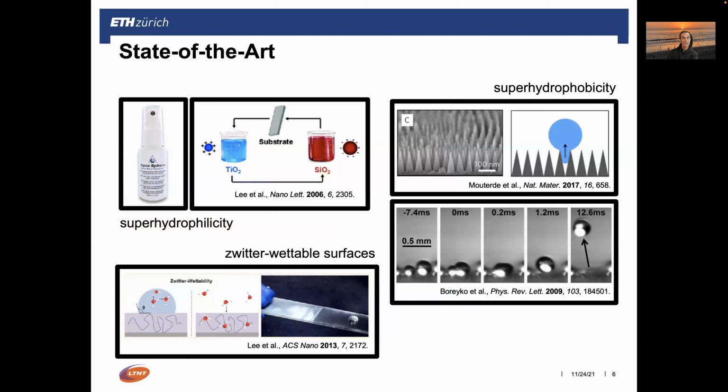The most interesting and more commercially available one, here on the left, is simply making the surface superhydrophilic. So we don't have these small droplets, we have a thin layer of water, and we mostly alleviate this fogging. Unfortunately, as you know, if you bought some of these liquids, they don't work very well, because the liquid dries and we almost immediately have limited effects. The film has non-uniform condensation on islands of wet and dry spots, and those things don't work very well.